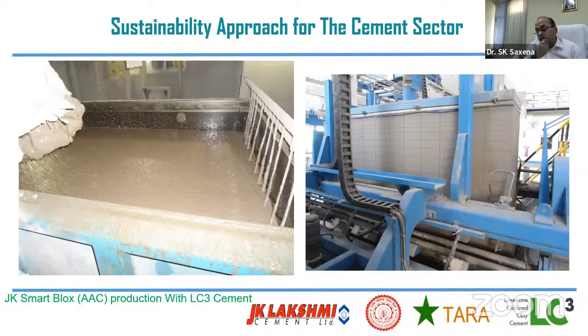And one of the most important, which I would like to inform, is that this LC3 we tried also in manufacturing of autoclave aerated concrete blocks, which we have a capacity of 500 meters cube per day in the same premises of JK Lakshmi Cement grinding unit at Jhajjar, and we are regularly producing autoclave aerated concrete blocks there. And there was a demand of autoclave aerated concrete blocks for making an administrative block of Swiss Embassy,